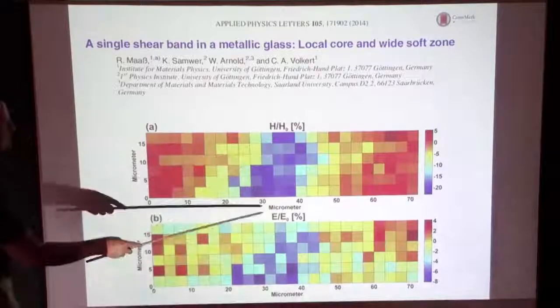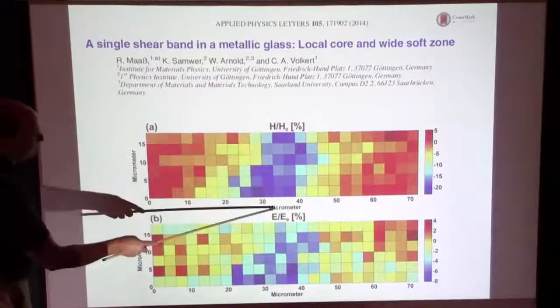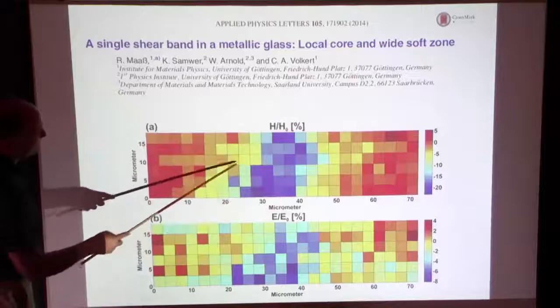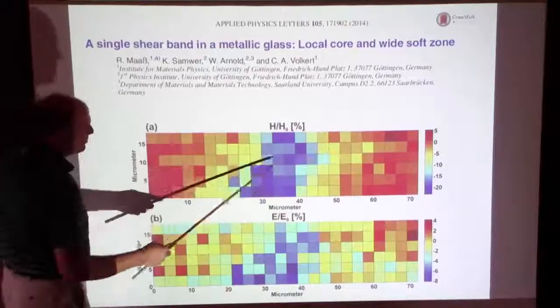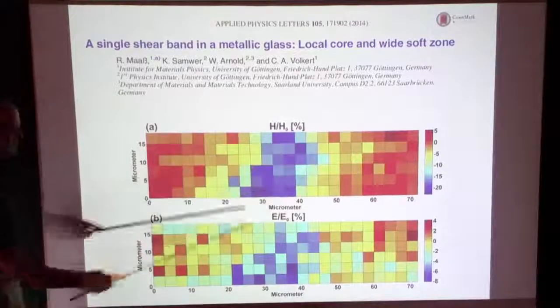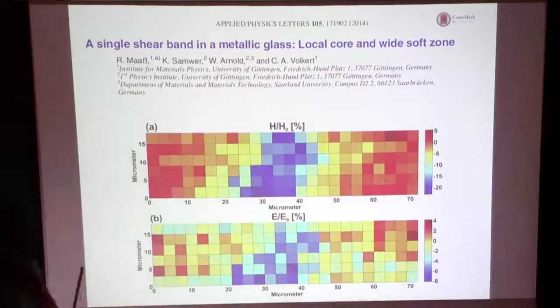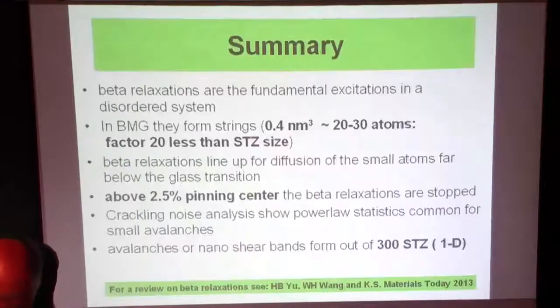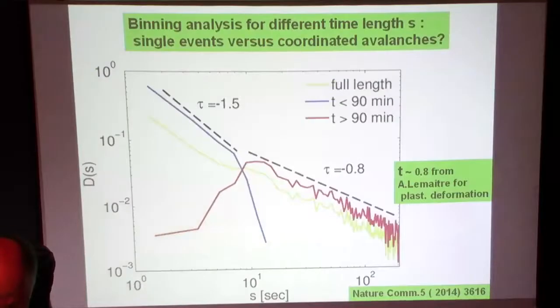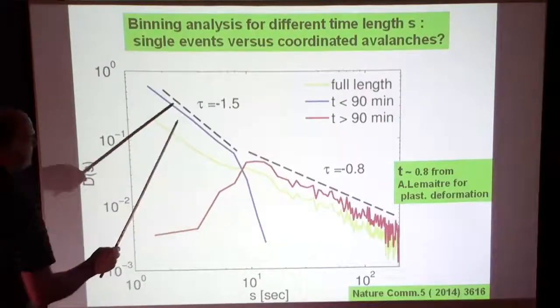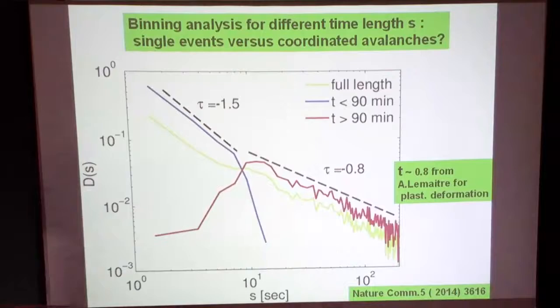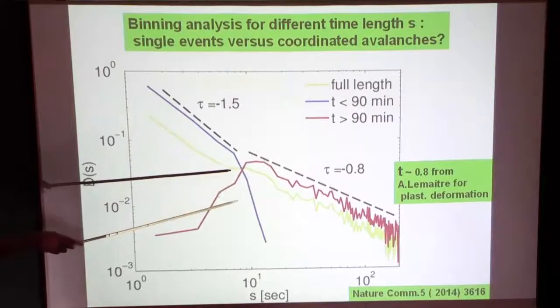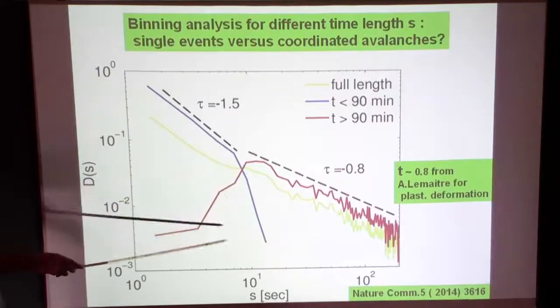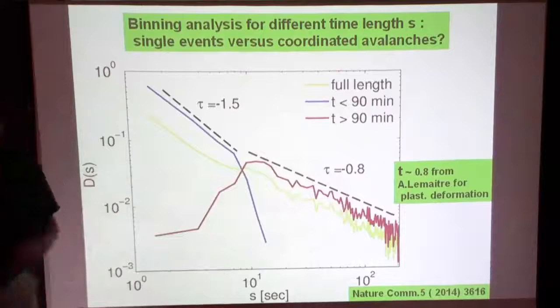Actually, if you measure now with nanoindentation, this is a shear band, in micrometers here, which is located there, but even far away from that shear band, you see that the hardness, for example, or the modulus is changing too. So the idea, coming back to this crossover, which we debated a long time ago and finally published it also, but it's not solved. It is not system spanning like Robert Ecke discussed, because that would show up as a maximum, if I understand it correctly, right?